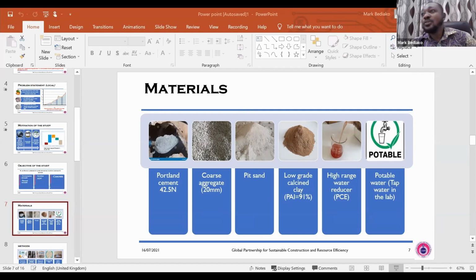Well, so these were the sorptivity values. The point of interest here is that the clay pozzolan reduced the sorptivity value. It was lower between 10 and 20%. The RCPT results were also very interesting. These are the key things. If you want to understand it, we can pick the ASTM C1202 to actually look at what the values mean. So no concrete was within the high range. But the key thing is that a longer period of curing showed that higher volumes of the pozzolans within the concrete resisted the ingress of chloride. So at 40 and 50%, it was within the very, very low range at late age of curing.